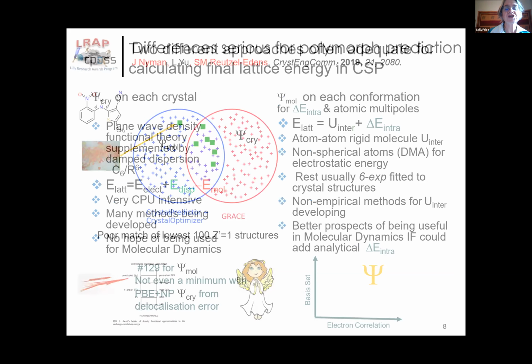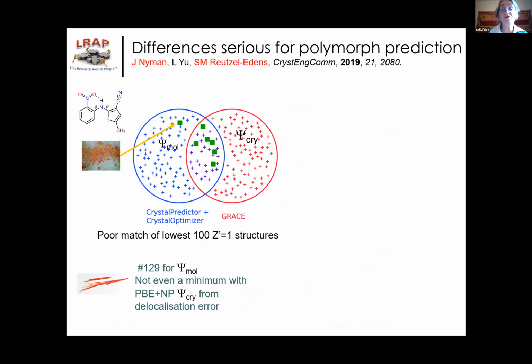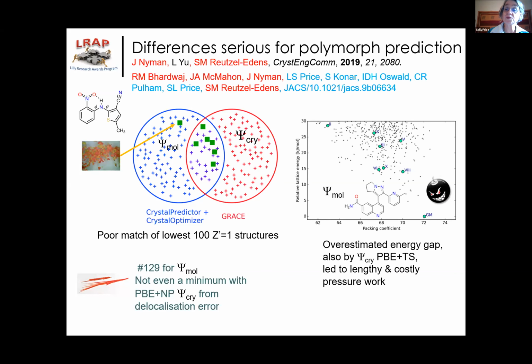Now, the differences between these different approaches to evaluating energies are sort of converging, but still there's a long way to go, as can be seen by this comparison of the 100 lowest energy structures produced by two searches. This is for this molecule ROY that I showed you, and it's comparing that search with one done by the GRACE structure. And you can see that only 6 of the polymorphs were found by both methods. A lot of structures aren't overlapping. And worst of all, the orange needles were outside the top 100 for our method and weren't even a minimum on the PBE dispersion corrected surface. Another embarrassment was our original search had the global minimum far lower in energy, and so we were overestimating how much of a danger it was that that structure would be found.